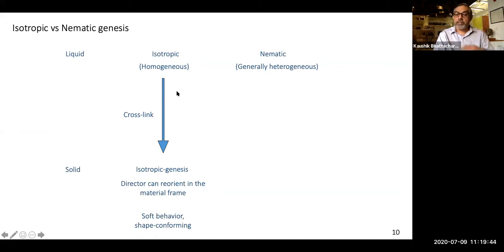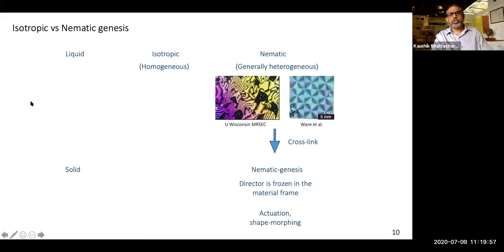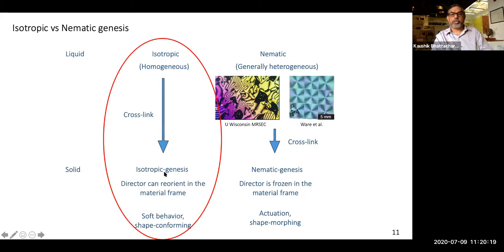And you will find that this material behaves in a soft way and has applications for changing shape and for draping, shape conforming. Whereas if I were to start again with the liquid, but now cool it down to a nematic state and then cross-link, you find that this material is very stiff. It has no soft behavior. But by patterning the way the nematic is done, by using liquid crystal technology, I can use it for shape actuation and shape morphing. So let me begin by describing the isotropic genesis material, and there I'll go through the entire story and only talk about glimpses here, and then come back and talk about photo actuation.